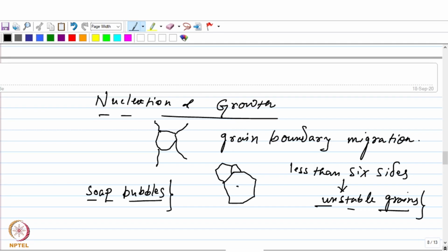And if you notice carefully, you would see that before disappearing, they would actually come down to a shape having only 3 sides, because this is the most unstable shape in a system like this where you have grains and grain boundaries. Okay, so if you look at the ones which are disappearing, you would find that before disappearing, somewhere a triangular grain like this one will form. Okay, and now if you see in the next stage, after a certain time interval, you would see this grain has disappeared.